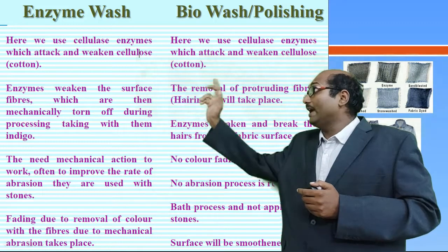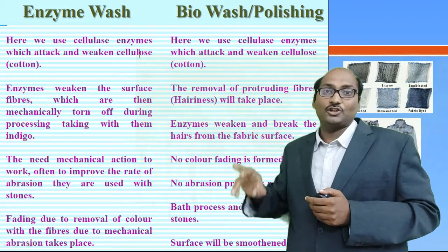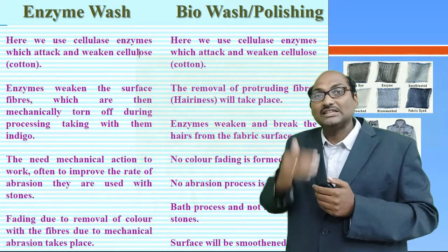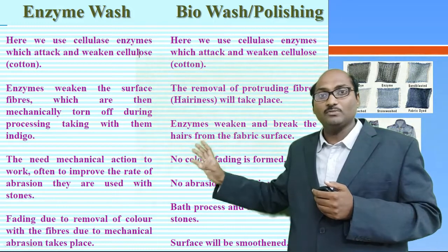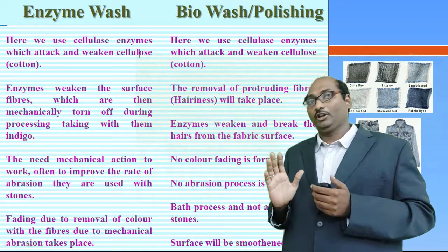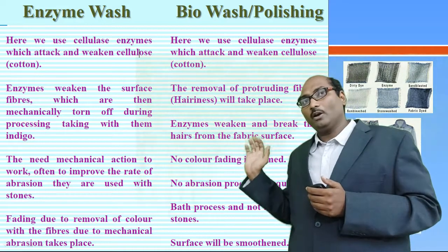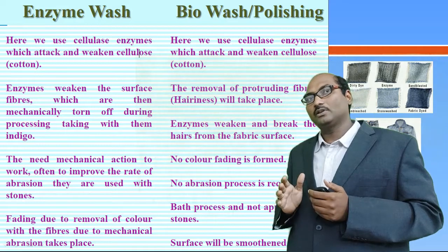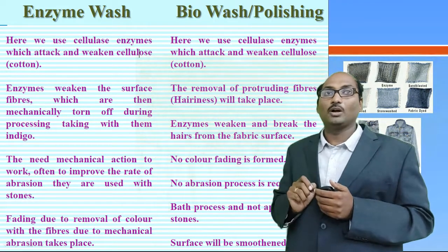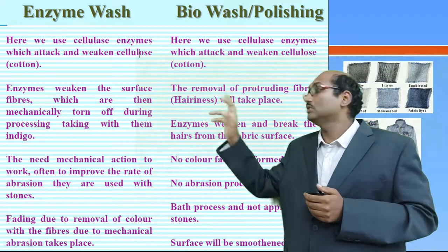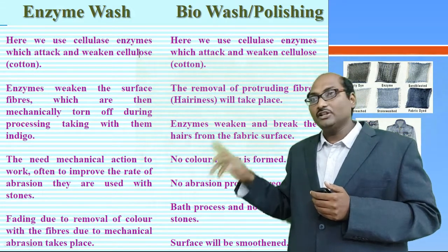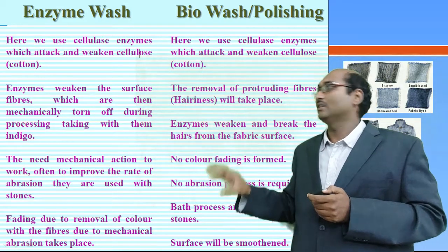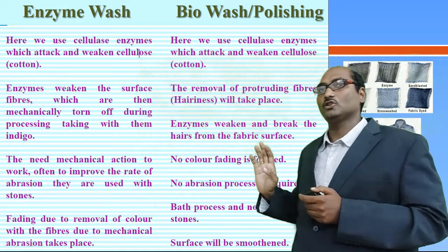Understood? So enzyme wash requires mechanical action to work and improves the rate of abrasion, meaning whatever happens in 60 minutes will be completed in only 30 minutes by adding enzymes. But in case of bio wash, no abrasion process is required, and the bath process is not applied with the stones in case of bio wash. But in case of enzyme wash, stones should be added. And in enzyme wash, fading due to removal of color with the fibers due to mechanical abrasion takes place. But in terms of bio wash, there is no fading.